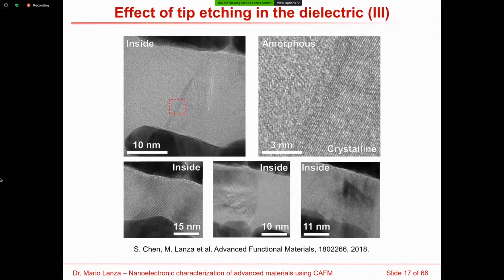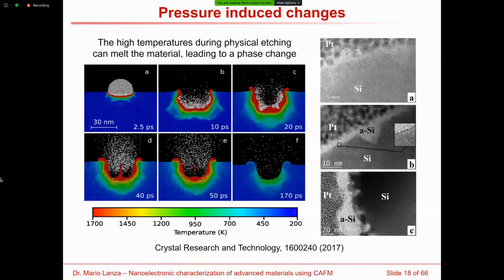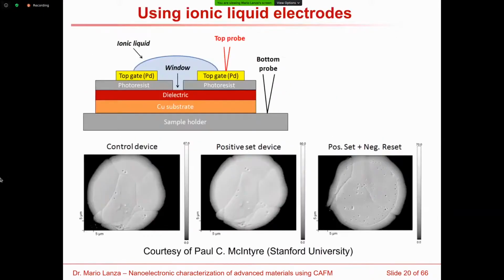So in order to avoid this problem, when I was working at Stanford University, together with Professor Paul McIntyre, we developed one interesting method to apply electrical stresses into dielectrics using ionic liquids. Instead of one solid metallic electrode, we use an ionic liquid conductive electrode, which is what you can see in this schematic.